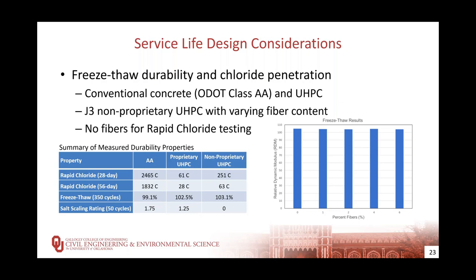We found that the proprietary UHPC had the best performance with a negligible charge passed, but that the non-proprietary UHPC exhibited a very low classification with only 63 coulombs passed at 56 days of age. Both UHPC mixtures exhibited significantly less charge passed than the conventional deck concrete.